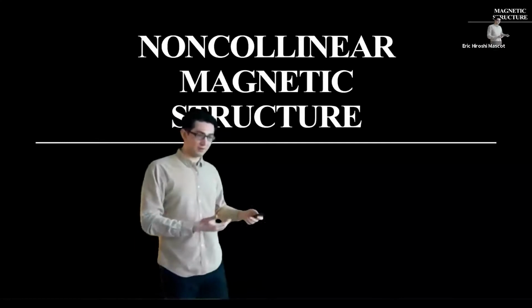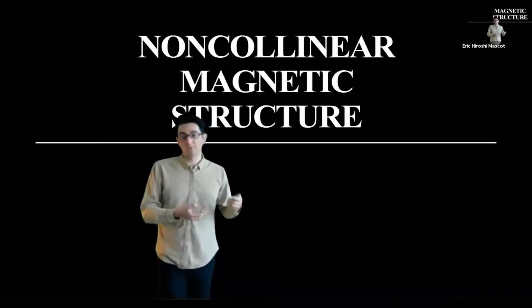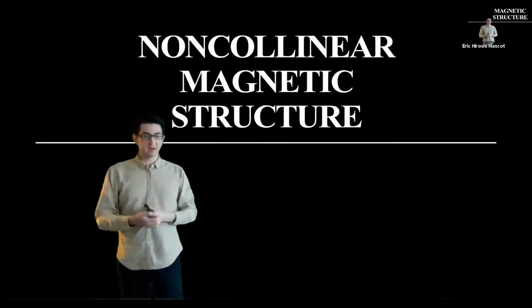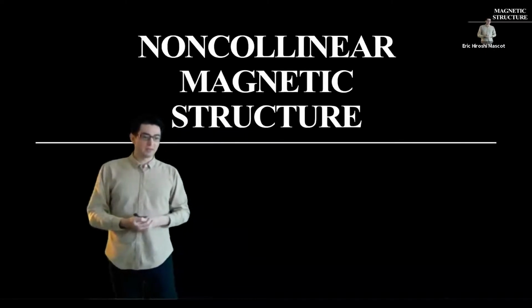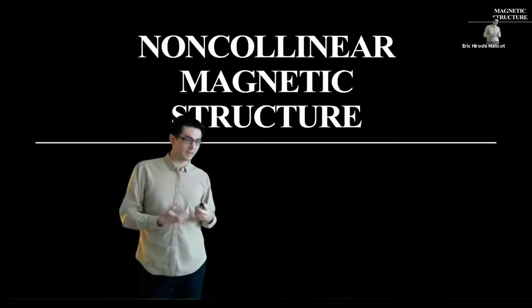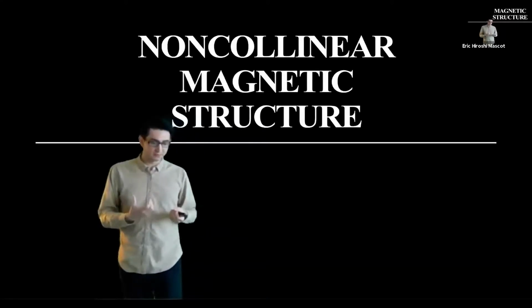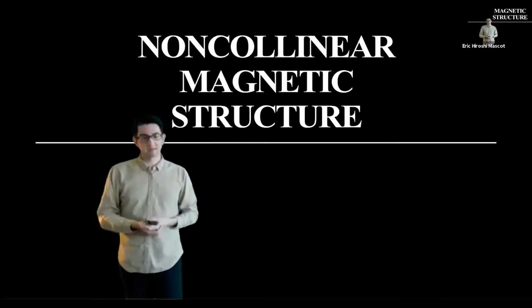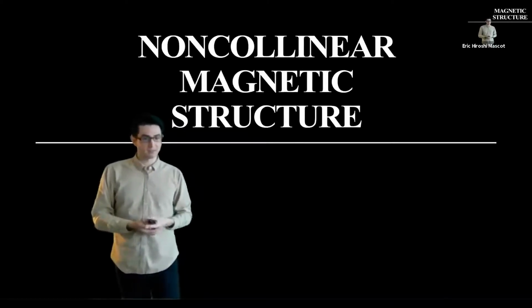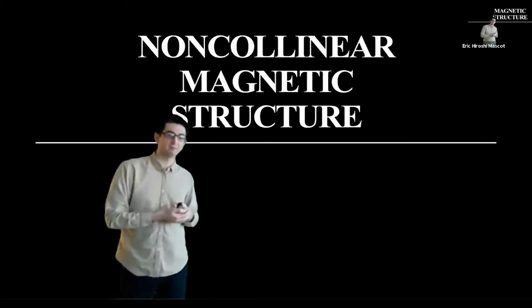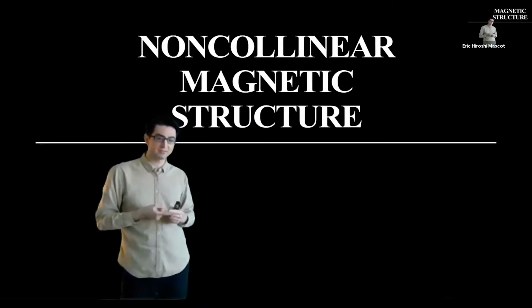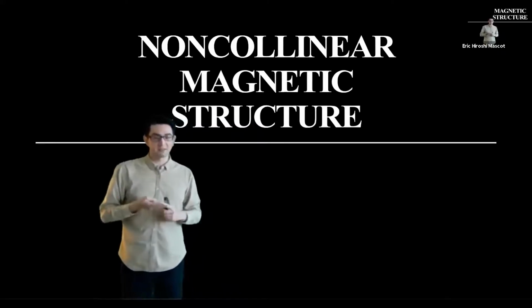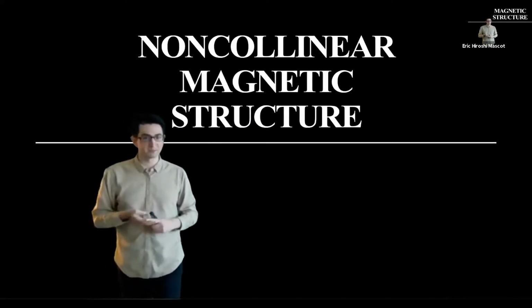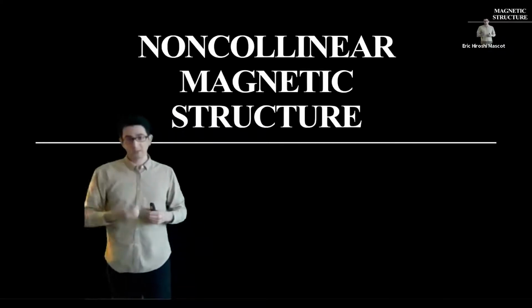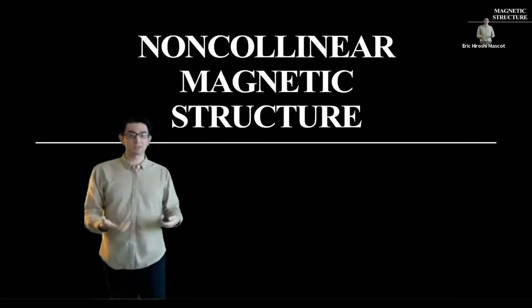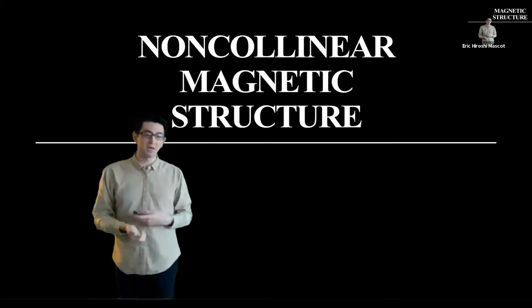Yeah, so far I focused on ferromagnetic ordering. So one of the problems that come from these systems is that it's very hard to change the topological phase, because in the phase diagram that I showed, we have the magnetic exchange interaction and the chemical potential. And these are material properties that are difficult to tune. So instead, can we use magnetic structure as a tuning parameter to be able to go between phases?